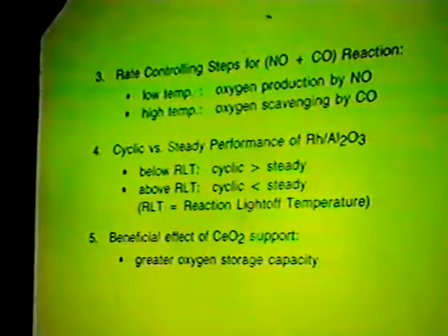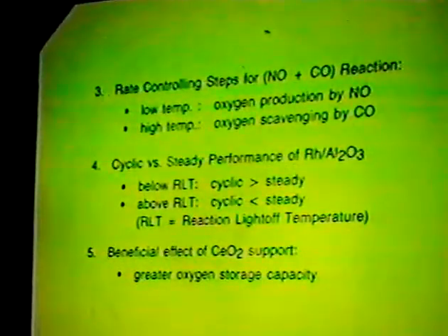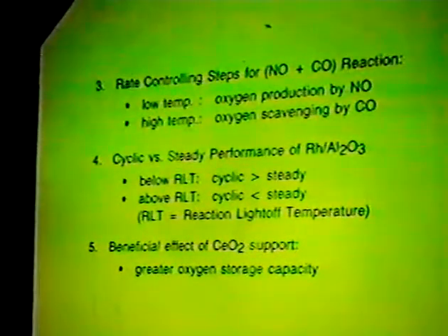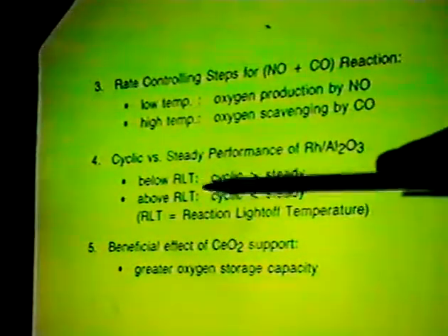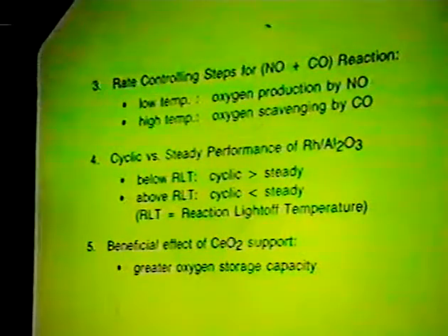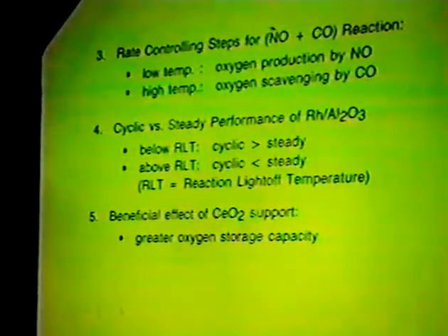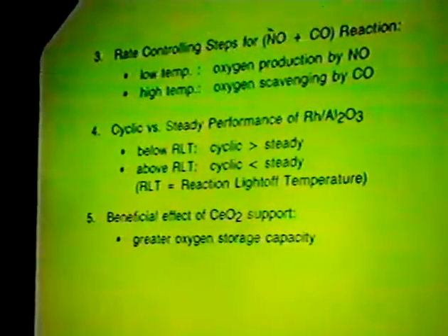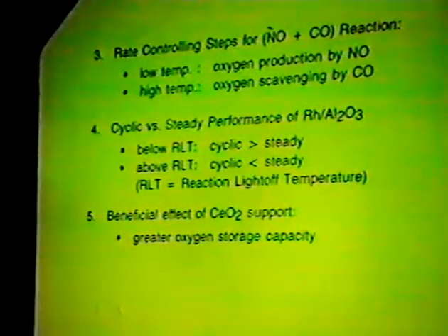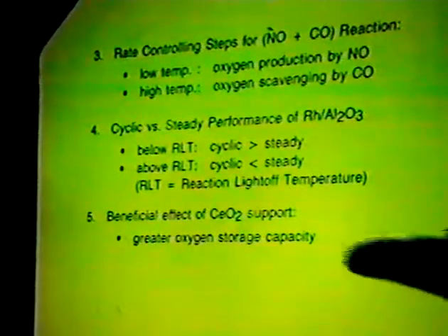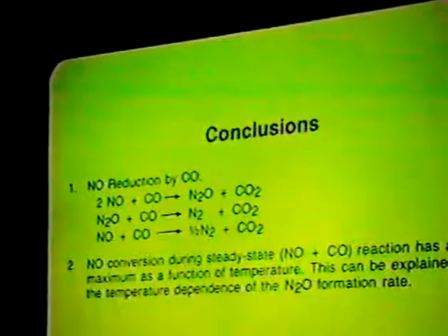And comparison of cyclic operation and steady operation shows us the same principle, which is that below the reaction light-off temperature, cyclic is better, and above the reaction light-off temperature, steady is better. We also observed the support effect, which we attribute to the greater oxygen storage capacity. And we are continuing to study this area. Thank you.